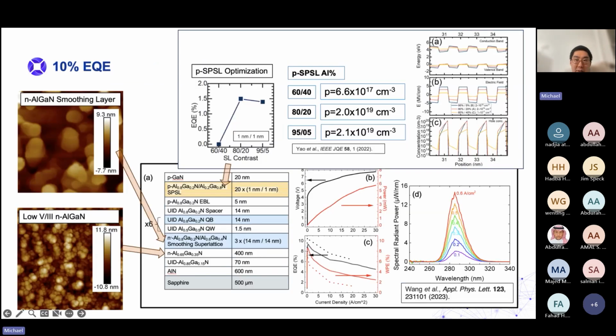So with these technologies and with optimization of the p-type material, so this is a short period superlattice where we have 1 nanometer of low aluminum percentage AlGaN and 1 nanometer of high aluminum percentage p-type AlGaN. And in Dr. Yifan Yao's work in 2022, we found that 80% and 20% aluminum gave us the best efficiency. Theoretically, 95 and 5 would give us more holes, but 80-20 is more transparent because of the 5% aluminum material absorbing too much light. And this results in LEDs with efficiencies of 10% EQE, 10.6, and 8.6% wall plug at 285 nanometers, as shown here. And this was published in 2023.